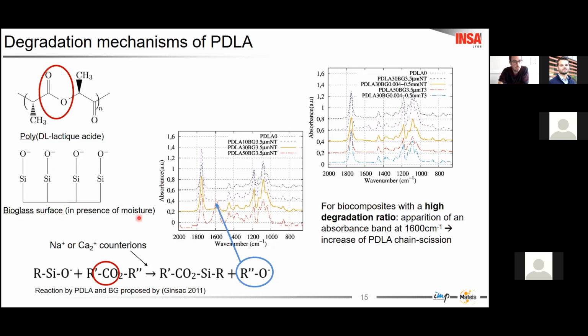In fact, in the presence of moisture, the SiO- on the surface of the bioglass are associated with the counterions that can provoke the rupture of the ester bonds of the PLA, which accelerates the hydrolysis of PLA.